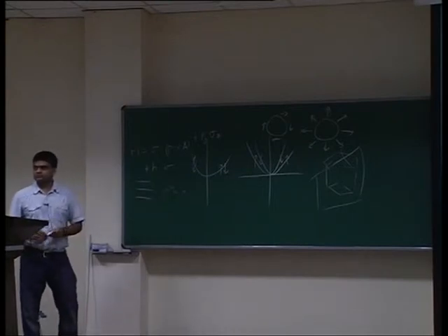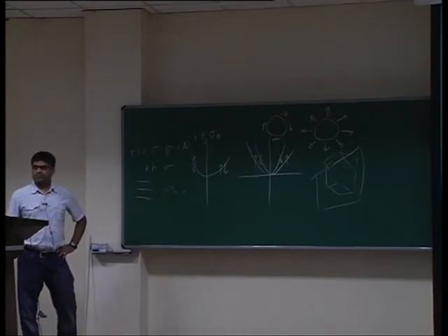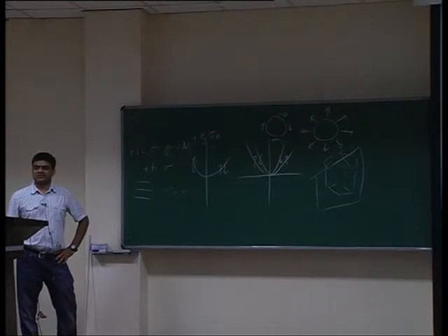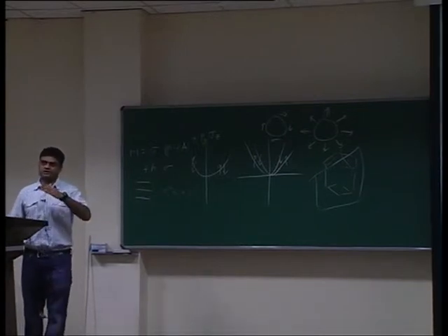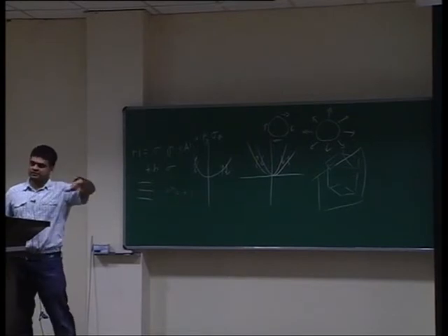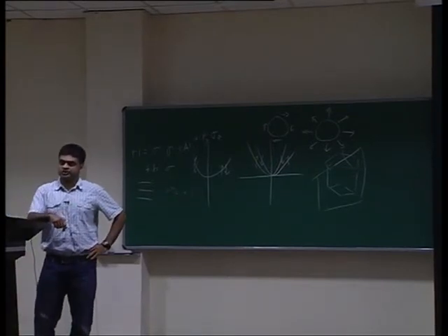Okay, I have a question about how the spectral function would behave at the Weyl point, because we have some spectroscopic level on the Weyl equation. So the density of states is very small. It goes as the square of the energy. So it may be hard to tell from an insulator actually. You'll have to be able to track this density of states going to 0 as the square.